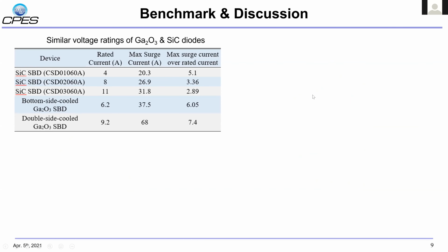Finally is our benchmark and discussion. Contrary to popular belief, gallium oxide Schottky barrier diodes with proper packaging, especially the double side cooling packaging, show high surge current capabilities. The double side cooled gallium oxide Schottky barrier diodes with a 3 × 3 millimeter square Schottky contact area can sustain a peak current over 68 amp, with a ratio between the peak surge current and the rated current superior to that of the similarly rated commercial silicon carbide Schottky barrier diodes.